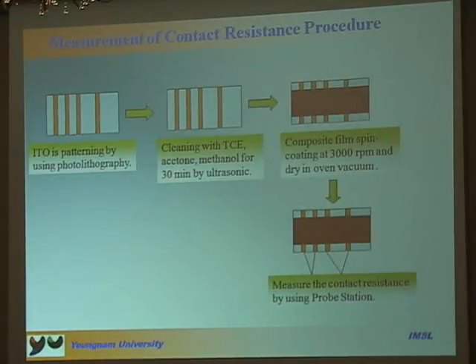Now I'm going to talk about the measurement of contact resistance procedure. First, ITO was patterned by photolithography technique. After that, the sample was cleaned by TCE, acetone, and methanol for 30 minutes by ultrasonics. After that, the composite film was spin coated at 3000 RPM and dried in a vacuum oven. After that, we measure the contact resistance using a probe station.